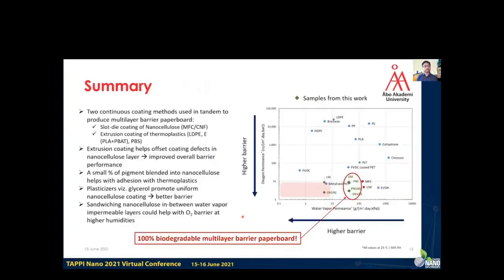So in summary, we use two continuous coating methods in tandem to produce a multi-layer barrier paperboard, by slot die coating of nanocellulose followed by extrusion coating of thermoplastics to produce this paperboard. Extrusion coating helps offset any coating defects in the nanocellulose layer and improves the overall barrier performance.